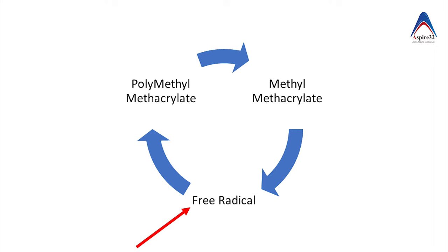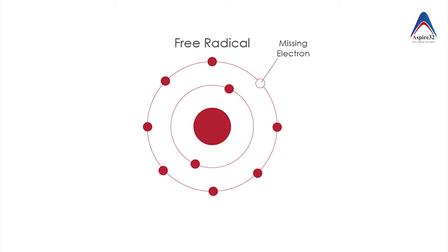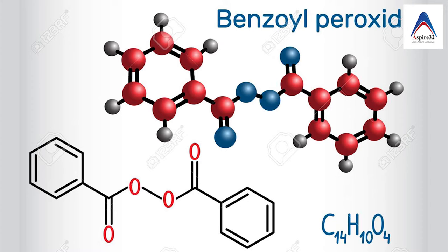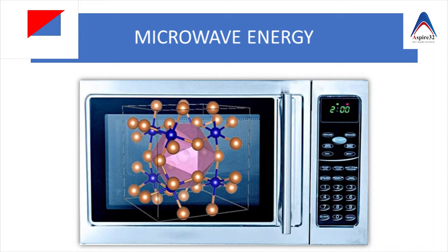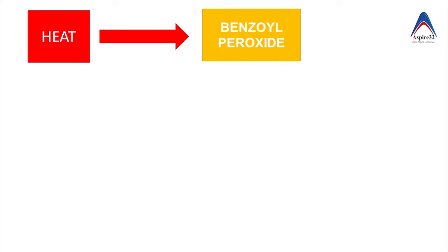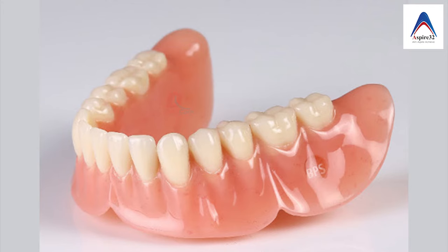The process of polymerization is very simple. We want to convert methyl methacrylate to polymethyl methacrylate, but in order to do that we need free radicals. This free radical is very important for the initiation of the reaction, and that's why we need substances which start this chain reaction by giving the free radical — these substances are called initiators. Most commonly it is benzoyl peroxide which is used as the initiator, but this initiator has to be activated. You can activate benzoyl peroxide by using thermal energy, for example by heating the acrylic material, or you can also use microwave energy. In this reaction, heat activates the initiator benzoyl peroxide to form the free radical, and once the free radical reaches the methyl methacrylate, the polymerization reaction starts, converting the material to polymethyl methacrylate.